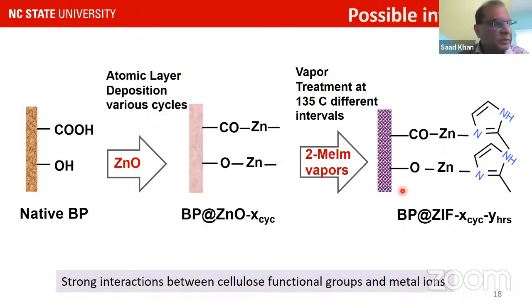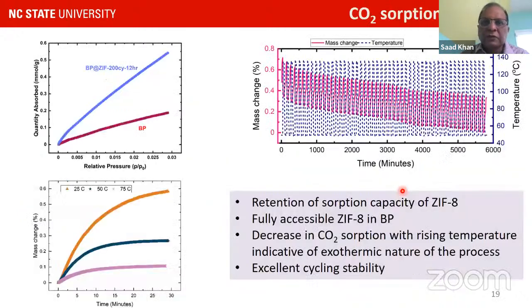So the question is, does it work, and how well does it work? I'm going to show you some results without going into detail. The first one here is showing you CO2 absorption. This is just for pure banana paper, and this is for banana paper with MOF. One of the things I want to point out is that the absorption we are getting is in the same range, and almost the same as what we get with the pure MOF. This is suggesting that we are not in any way impeding the efficacy of MOF.